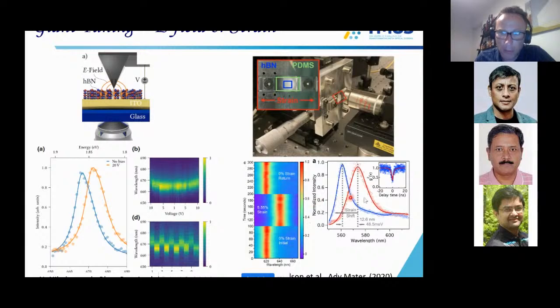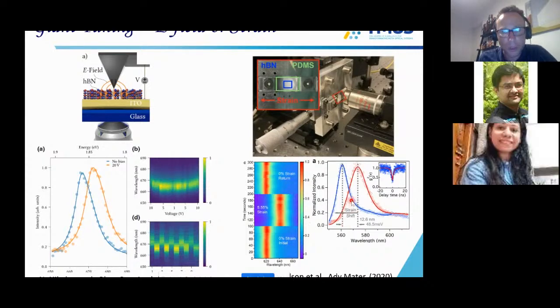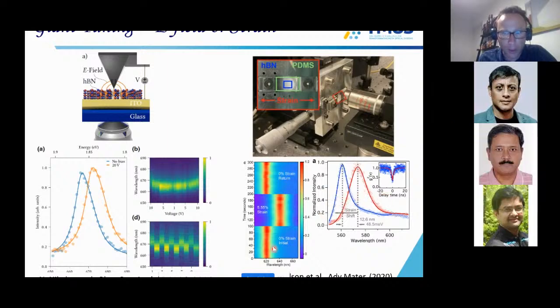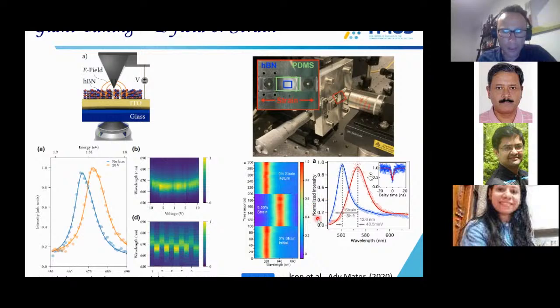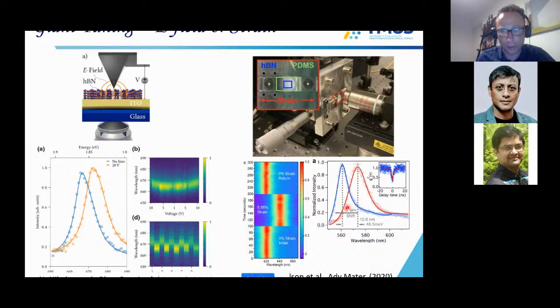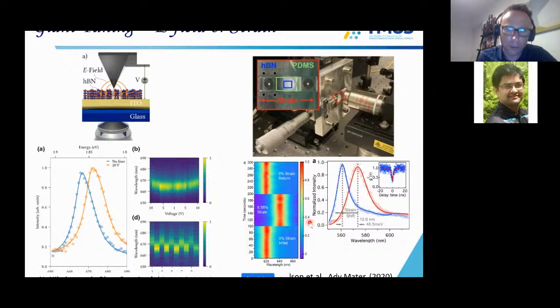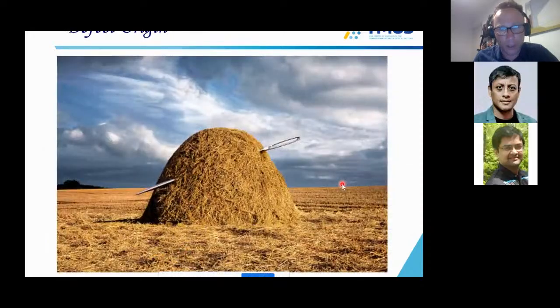You can really strain by about 20 nanometers or so. And I remind you that this is a single defect, which means that we are studying a single atom in a solid at room temperature, and we manage luminescence controllably by about 20 nanometers. No other system, including diamond and silicon carbide, can give you that on a single photon level. So these results really are very cool, and this is probably the best sensor you can ever imagine for your strain measurements. Okay, so the question is, of course, what is the defect?